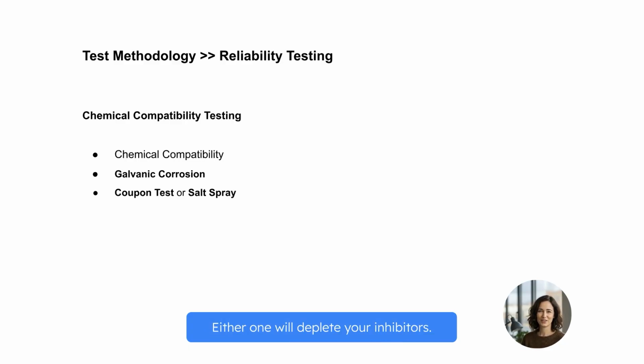On chemical compatibility, the enemy is twofold: galvanic corrosion from dissimilar metals and leaching from reactive polymers. Either one will deplete your inhibitors. Start with a basic coupon test or salt spray, ASTM B117, for a baseline. But for long-term reliability, you must run periodic sampling via ICP-MS. This is the only way to track fluid degradation at the molecular level.